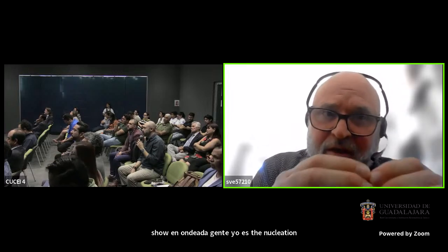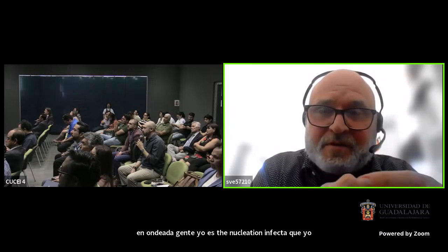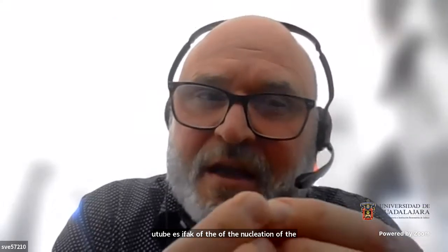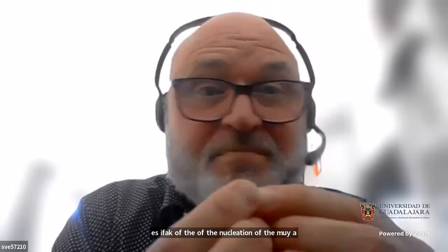Due to this effect of the nucleation, of the epitaxy of the polymer on the surface of the cellulose, we have a very good interaction. We have a very good interlocking between the fibers and the polymer. That gives us much better properties than just adding wood flour into PBS. So we have a very nice balance of toughness, strength, and modulus. That is the aim.